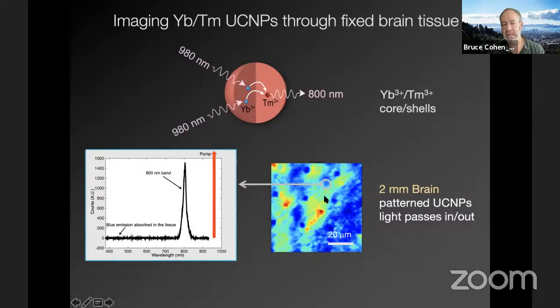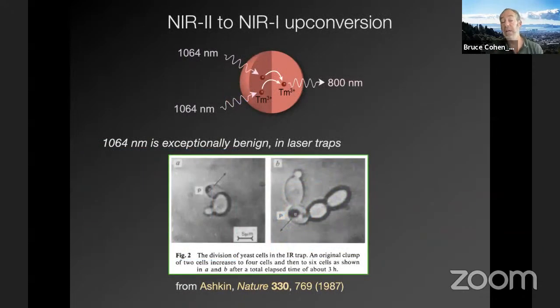So the nanoparticles are patterned on the surface, and you can get a spectrum of that image showing the 800 nanometer band. What we spent a long time trying to do was figure out wavelengths to use other than 980, both for multiplexed imaging, but also because water absorbs at 980. If you get to a certain confocal microscope power, you start to get water heating, which is not good. And a really classic wavelength is 1064.